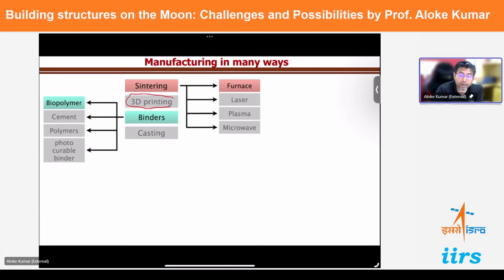We have done 3D printing with this slurry, whatever you saw. We have used different types of binders, and they have worked out very, very well. We have tried different types of casting. We have also tried sintering. In sintering, we have tried furnace sintering. Sintering is a technique where you make bricks by heating them together. So you put this brick, like this cast, into an oven, and the oven goes to a very high temperature, close to 1,000 degrees Celsius, and then the particles start to adhere themselves.